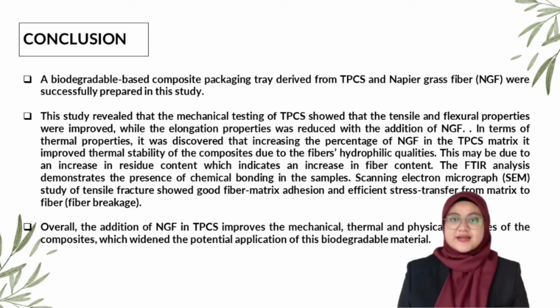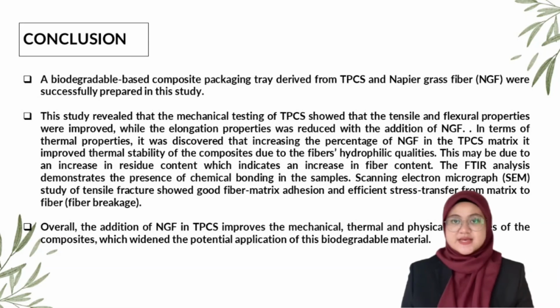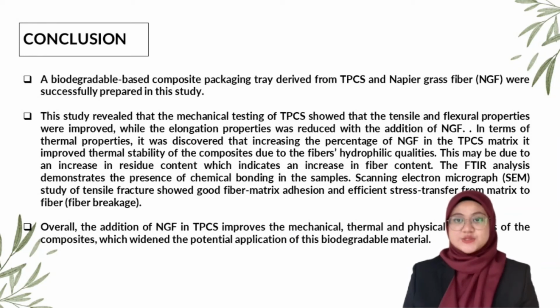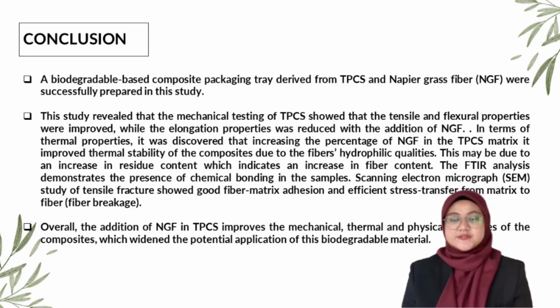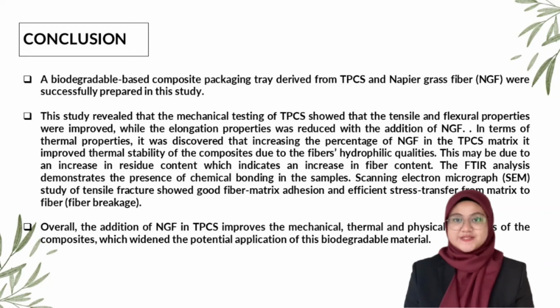The FTIR analysis demonstrates the presence of chemical bonding in the samples. The scanning electron micrograph, also known as SEM, that studied the tensile fracture shows good fiber-matrix adhesion and efficient stress transfer from matrix to fiber. Overall, the addition of Napier grass fiber in TPCS improves the mechanical, thermal, and physical properties of the composite, which widens the potential application of this biodegradable material.